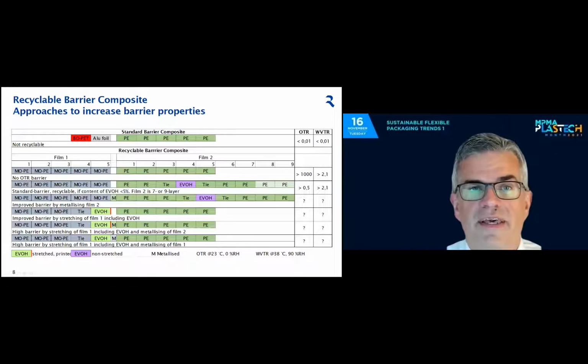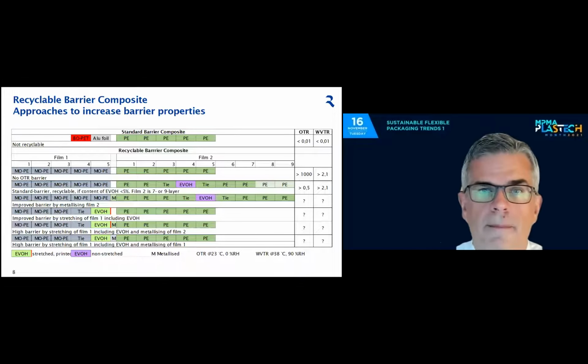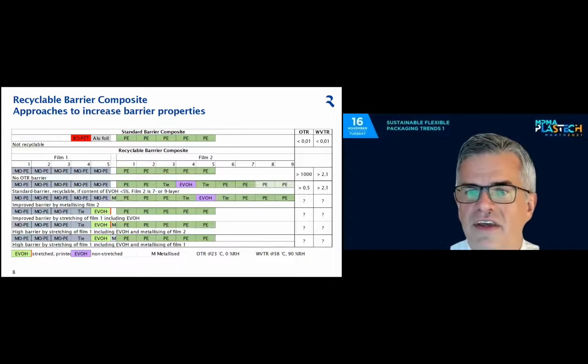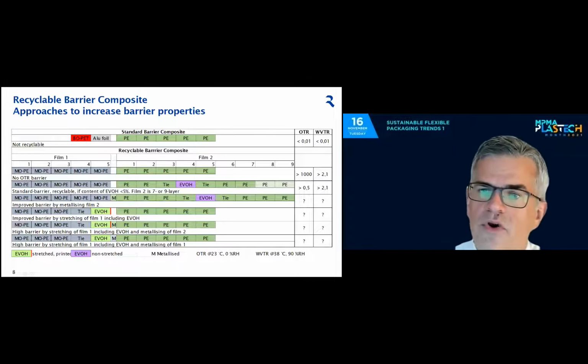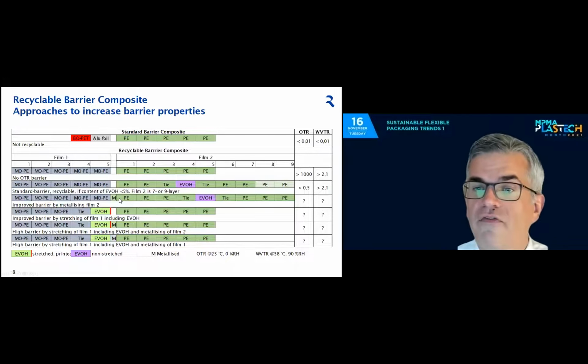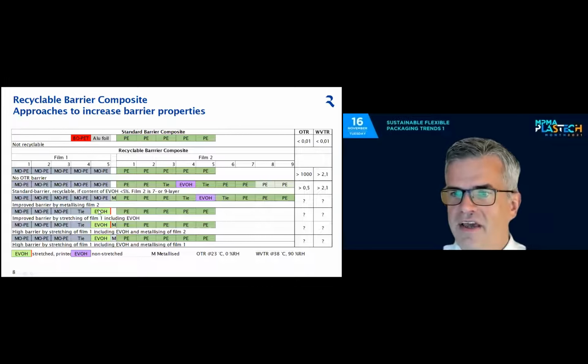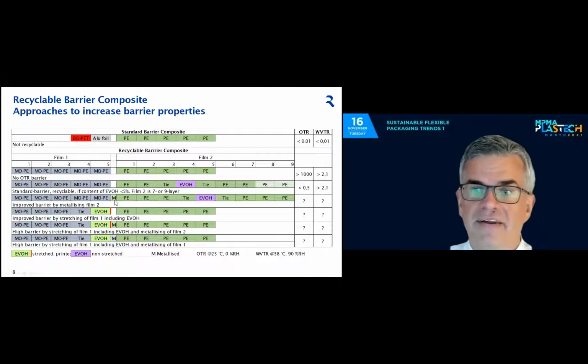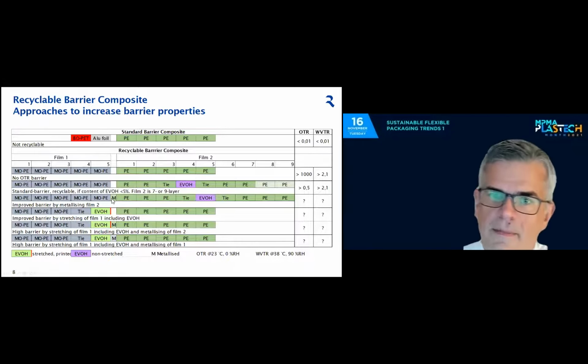However, for certain applications, this is not good enough. So what can we do in the next step to increase and to improve barrier properties? Well, we could, for example, do a metallization of my PE lamination film. So film number 1 is still stretched PE film. Film number 2 is a lamination film with EVOH, which is metallized on the surface.